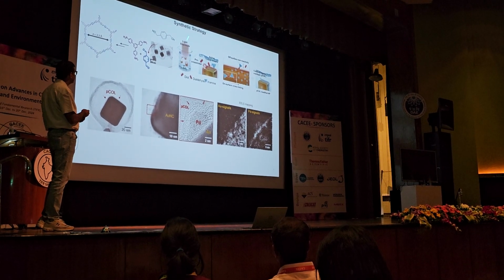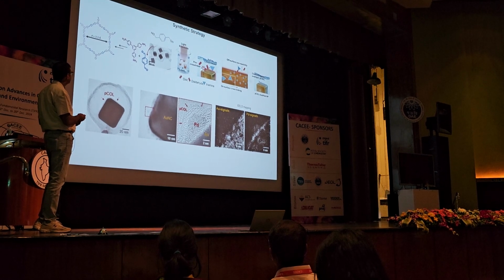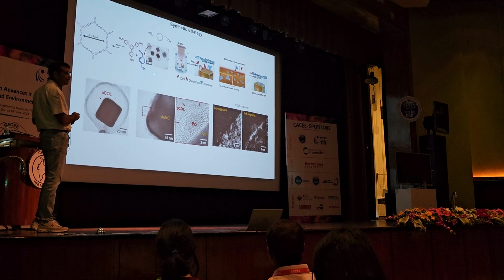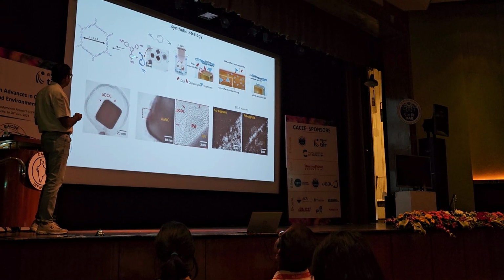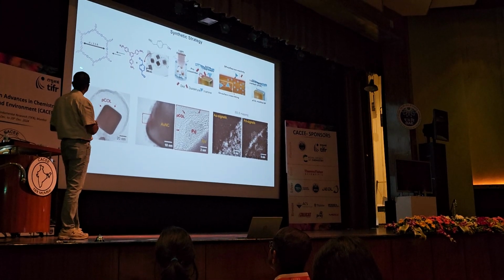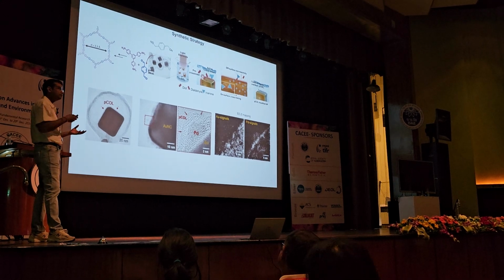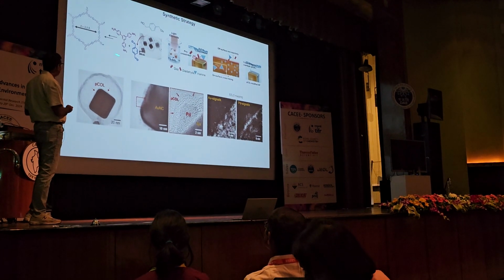Expose that solution to light. When you expose it, there will be activation on the surface, and you can take this diol, which will be converted in situ to this dialdehyde, and you throw in this triamine, which will condense with it, and that may create this kind of pore by simple covalent organic framework formation chemistry. So we got inspiration from COF chemistry and used it.